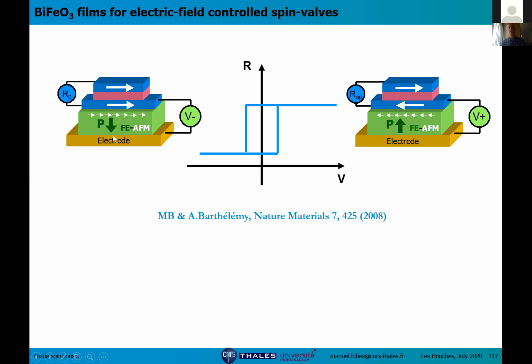When you switch the polarization, the spins in the multiferroic are switching as well. And if there's a coupling between the magnetization of the bottom ferromagnet and the spins in the antiferromagnet, this magnetization will also switch. And as a result, the resistance in the spin valve will change. And you will get this kind of resistance versus voltage curves.